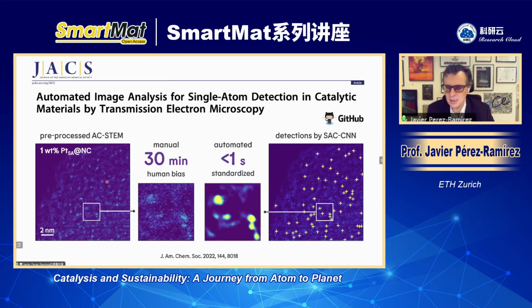Because first of all, we need a lot of microscopy time to characterize many samples, to visualize many samples. But most important, these many samples need to be analyzed. Somebody has to analyze this. And typically this is done by the microscopist. If you analyze one image as an expert microscopist in a manual fashion, each image takes half an hour of analysis. And actually there is even a human bias. That means depending on the eyes that analyze this image, some could say a single atom where someone doesn't see a single atom or sees a cluster instead.